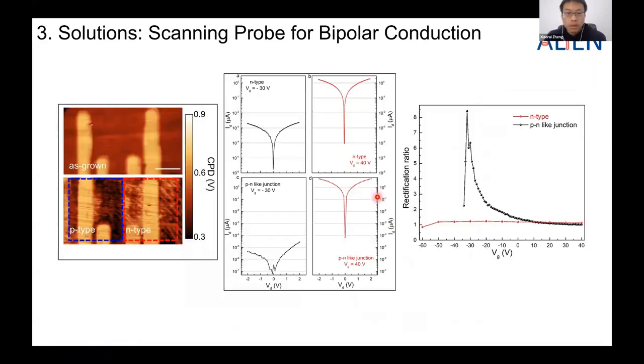Okay. So if we further look into the p-n junction we have created, as you can see, this is a KPFM image. The as-grown sample has a uniform CPD value, or contact potential value. After the p-n junction doping, we can see a contrast between the p-doped region and the n-doped region, and this is the p-n junction here. However, this rectification ratio of the current is also dependent on the backgating.